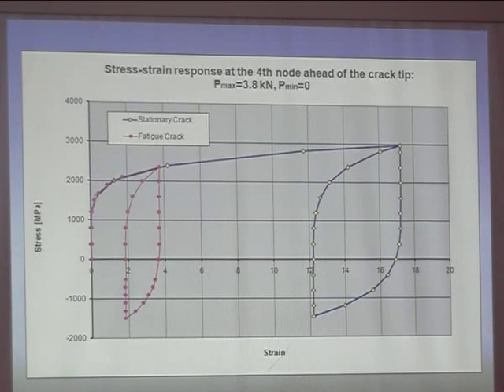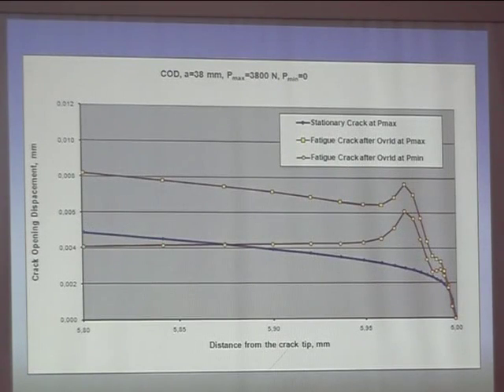And the results were pretty consistent throughout that case, but then it was interesting to see what's going on before and after overload. So we applied the overload and I propagated the crack by 1 or 2 elements. And we look at that, and that was surprising to me, because this is the displacement field after overload, and this is the displacement field at the minimum load after overload. So this is the maximum, this is the minimum.